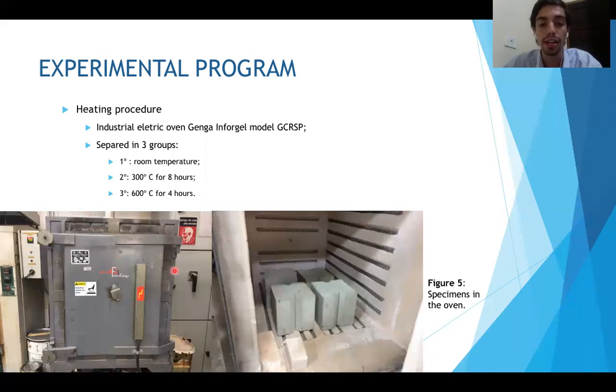After grooving, the specimens were heated in an industrial oven. A group of 4 specimens was kept at room temperature to establish a reference. A second group of 4 specimens was heated at 300 Celsius degrees for 8 hours, and a third group was heated at 600 Celsius degrees for 4 hours.